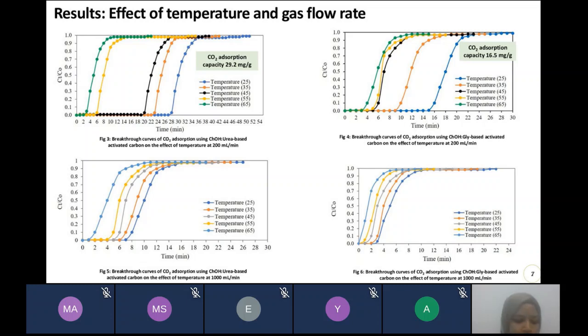Based on Figure 3 and Figure 4, it was noted that breakthrough becomes shorter and steeper at high temperature, indicating that the adsorption process is an exothermic reaction which describes physisorption. The maximum adsorption capacity was obtained at 25 degrees Celsius, which is 29.2 milligram per gram for the adsorbent modified with choline hydroxide urea at a flow rate of 200 milliliter per minute. Low temperature provides more active sites to be attached by carbon dioxide molecules and enhances the adsorption performance.